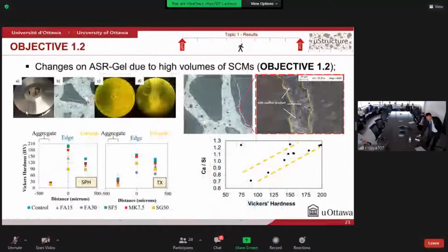And we tested the ASR gel in the cement paste, ITZ, and internally to the aggregate through a microindentation analysis, which gives us the mechanical properties of the ASR gel. In this case, the surface hardness, translated here as Vickers hardness, as we can see, increasing the SCM amount in the concrete, there's a significant decrease in the Vickers hardness for ASR gel in the cement paste or ITZ. However, within the aggregates, the average of the results are pretty much the same, indicating that SCMs do not have influence on the properties of the ASR gel within the aggregates.